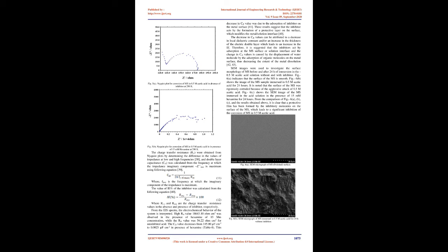The enthalpy of adsorption, ΔH°ads, was calculated according to the Van 't Hoff equation 30, 31, by plotting ln Cads versus 1/T with a slope of -ΔH°ads/R. Van 't Hoff plot. The negative value of ΔH°ads suggests that the adsorption of inhibitors is an exothermic process 29-34, which reveals that the inhibition efficiency of the inhibitor decreases with raising the temperature.